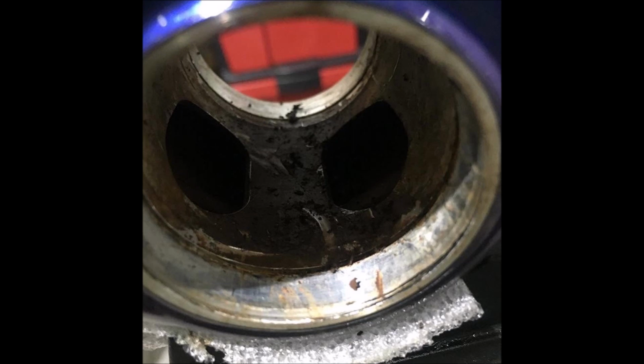You can see all the dirt build up. The problem with these frames is that water rushes in when you're washing or riding in the rain. Moisture builds up within the shell of the bottom bracket because it's made in two parts, and you have like a trough in the bottom of the shell that you can just see through those holes. And that trough is not in any way vented. There's no way for the water to escape other than tipping the bike backwards, and many people don't think to do that.